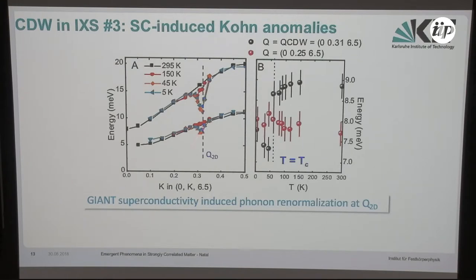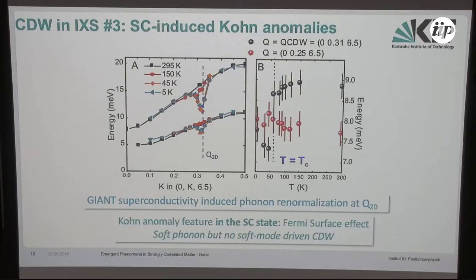And the third one is when I go into the superconducting state, I see a sharp phonon softening. It's actually a very decent softening, 15% to 20% of the phonon frequency. It's a big effect. When you do phonon spectroscopy, it's basically boring, you see nothing happening, and when you see this kind of big softening, you're surprised. It looks very much like the Kohn anomalies that we had in classical charge density waves, except that now it's induced by superconductivity, and it never goes to zero. So it doesn't look like a soft-mode-driven charge density wave à la Peierls.